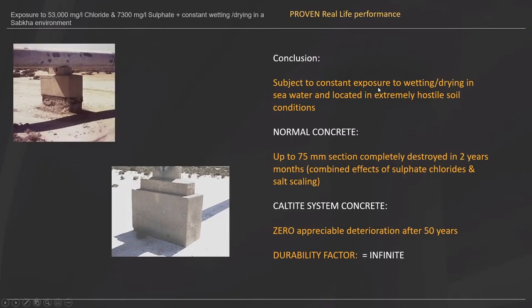So in conclusion, then, the wetting and drying of seawater located in extremely hostile soil conditions, normal concrete up to 75 millimetres was completely destroyed in 2 years, with the Caltite system, zero appreciable deterioration after 50 years. So it's an infinite durability factor.